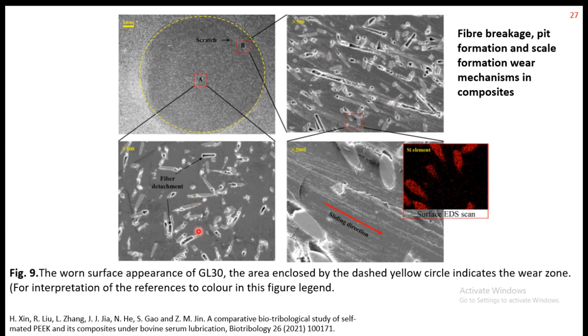However, if we look at the failure of the polymeric composites, in this case the glass fiber one, you can see lots of pull out of the fiber. These fibers are longitudinally arranged on the surface. So in the bulk they are random, but on the surface they are longitudinally arranged, and they get pulled out during the sliding that takes place. And as you know, this sliding is not full liquid film, but rather it is mixed, so there is always a possibility of dry interaction between the two surfaces.